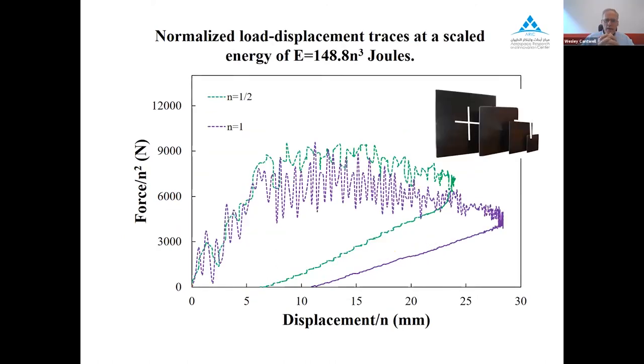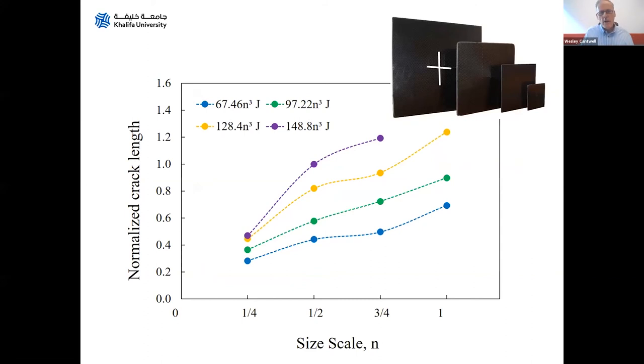But if we increase our impact energy, and if I remove the quarter and three quarters traces and just leave these two, then we start to see a difference. This is 148 N cubed joules. There, green is our N equals half, purple is our N equals one. And we see that this fiber fracture region goes on for much longer in the larger panel. And indeed, if we crudely measure those fiber fracture lengths in both the X and the Y directions, and we add them together and normalize it by the length of the panel itself.